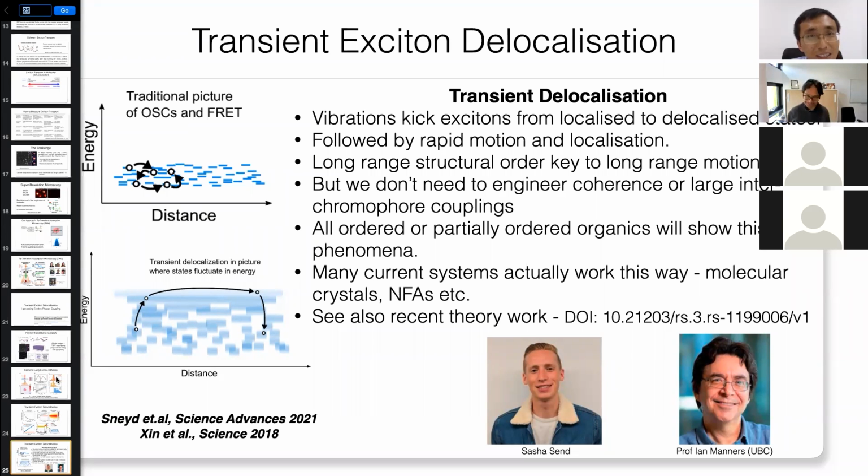Not necessarily. The requirement for high mobility of charges is normally that you require nearest neighbor coupling, and then you need long range crystallinity. Actually, it's harder to move charges than to move excitons. If you have a charge, it needs to go through this molecule, the next molecule, the next molecule, and so on. It can't jump through space. It needs to actually transport physically. But your exciton can jump from one point to another through space, because it's a Coulomb interaction. So if your energetic landscape is like this for the charge, then your charge will get trapped at each point. Whereas for the exciton, it doesn't care. It smooths over and it jumps. So in fact, the real thing is the long range order for charges, which is not so important for excitons.